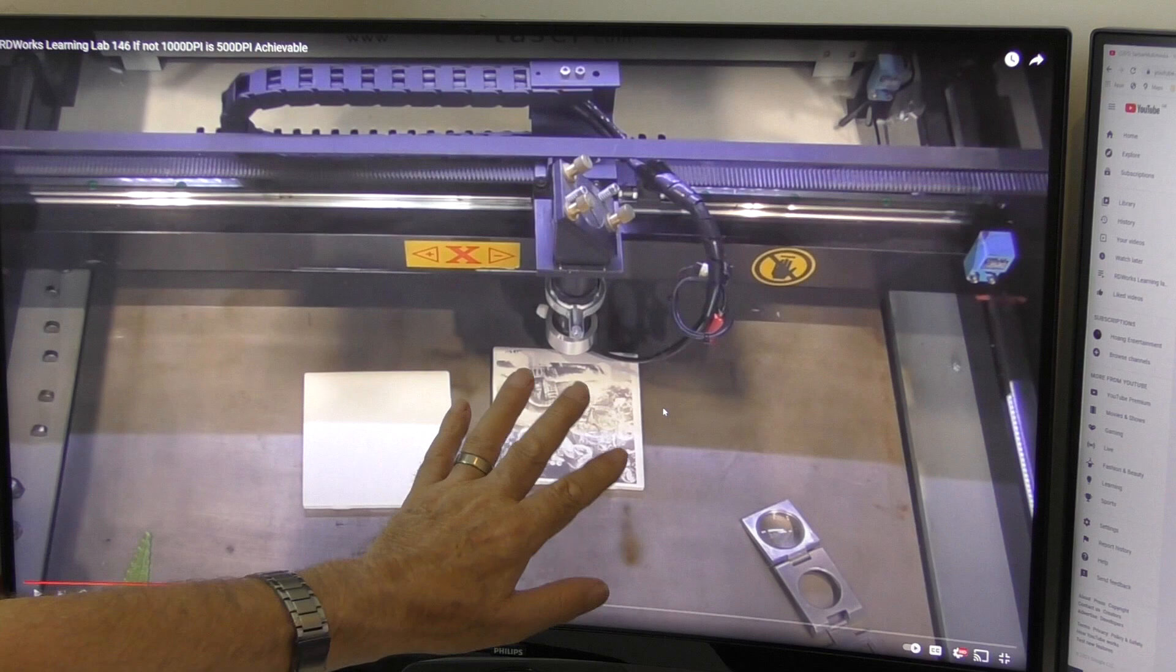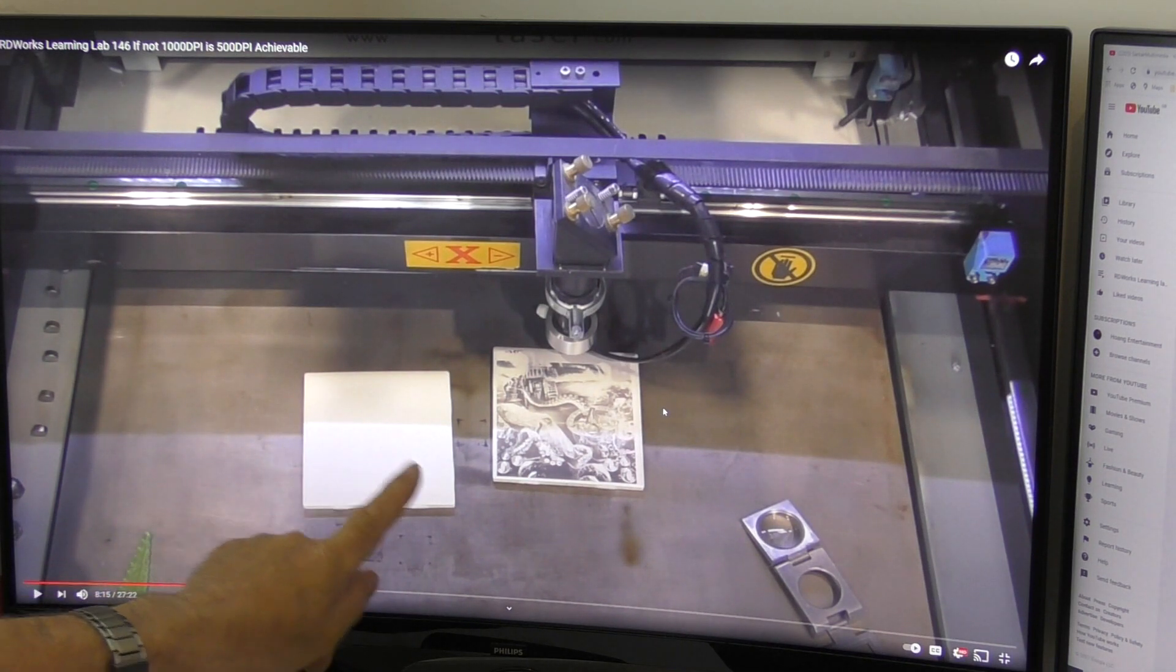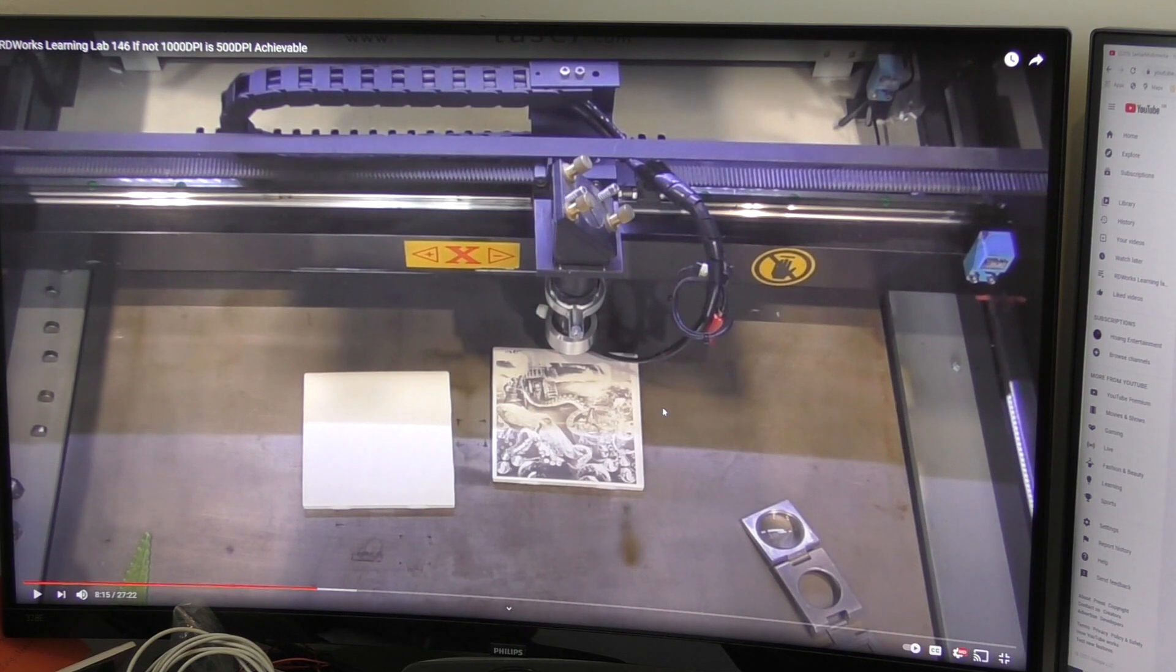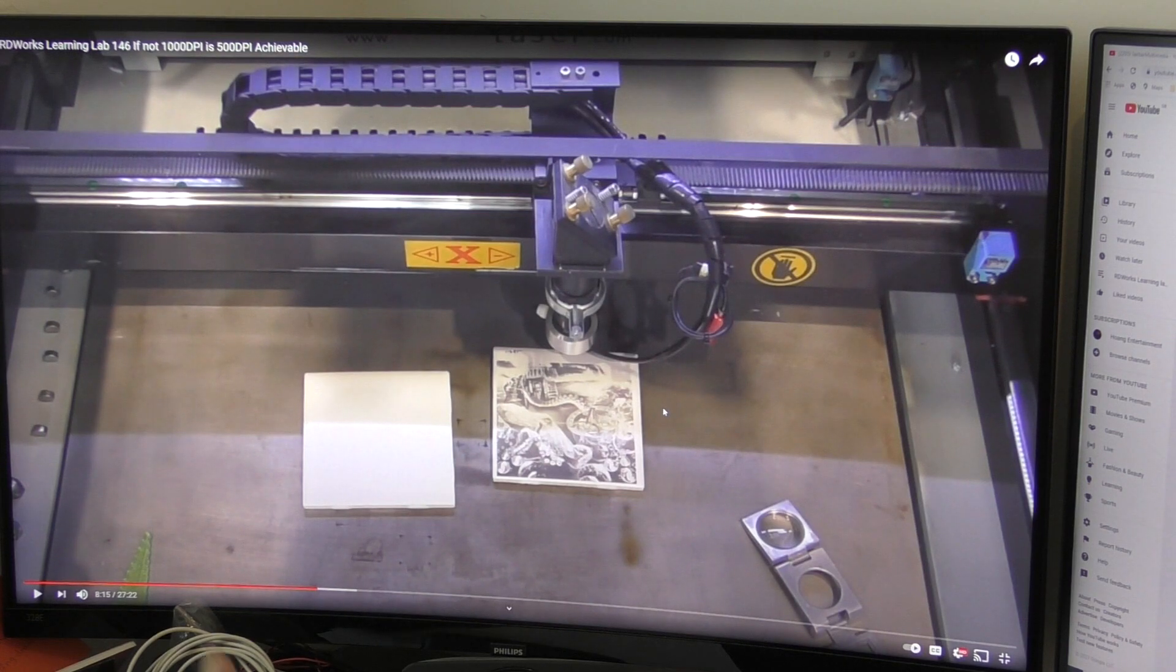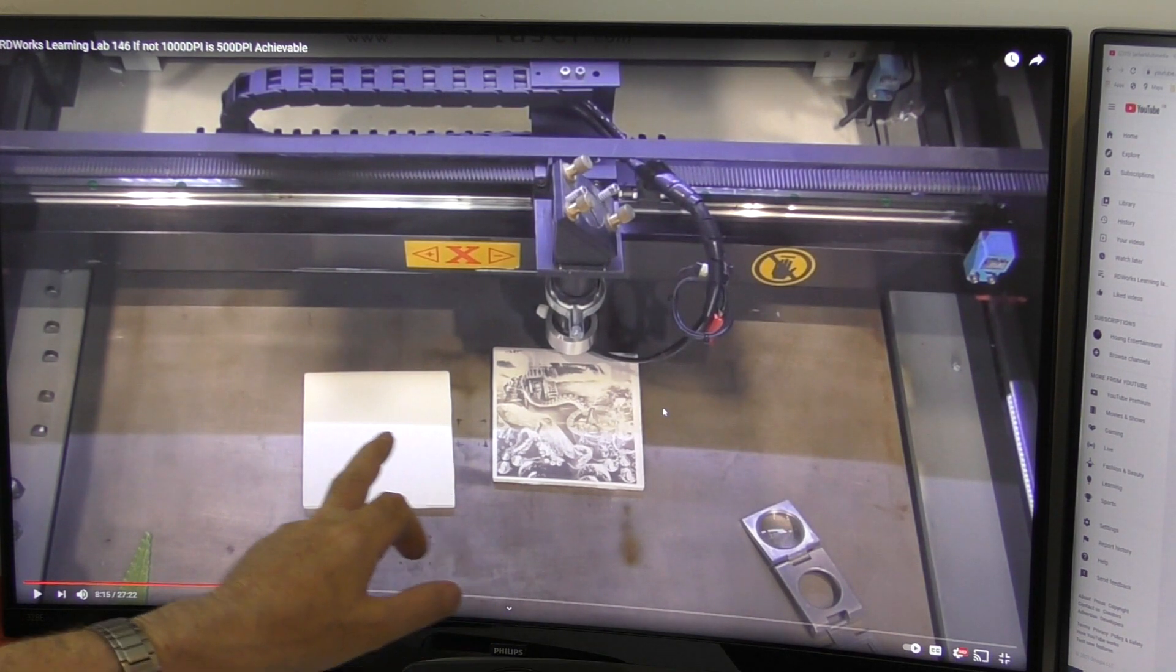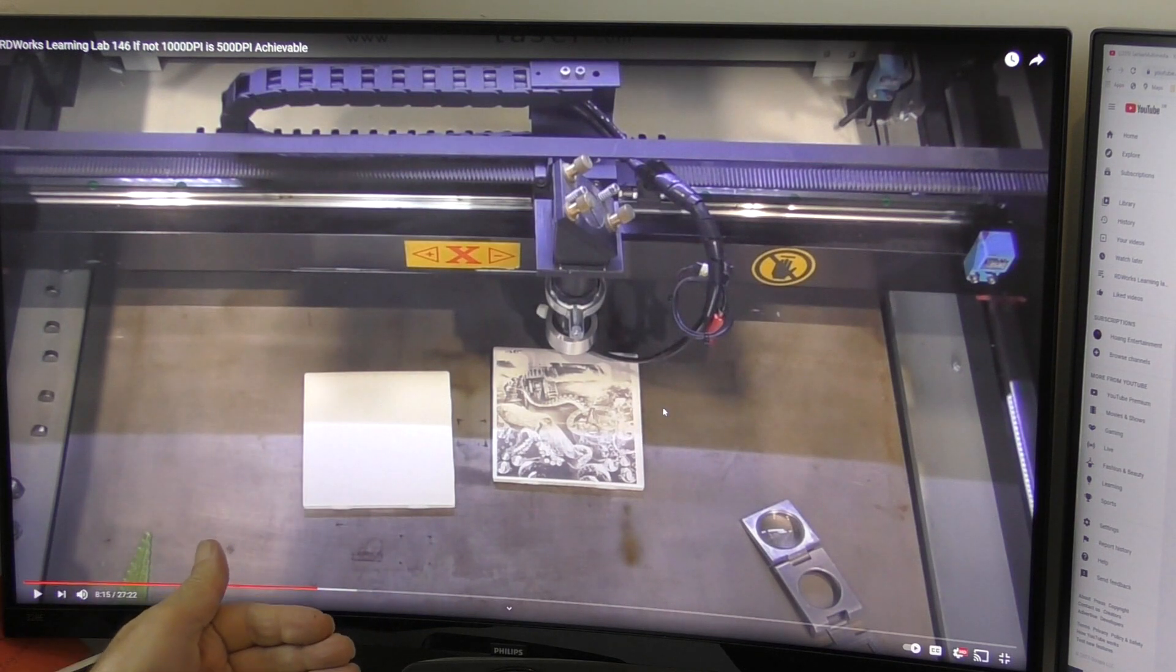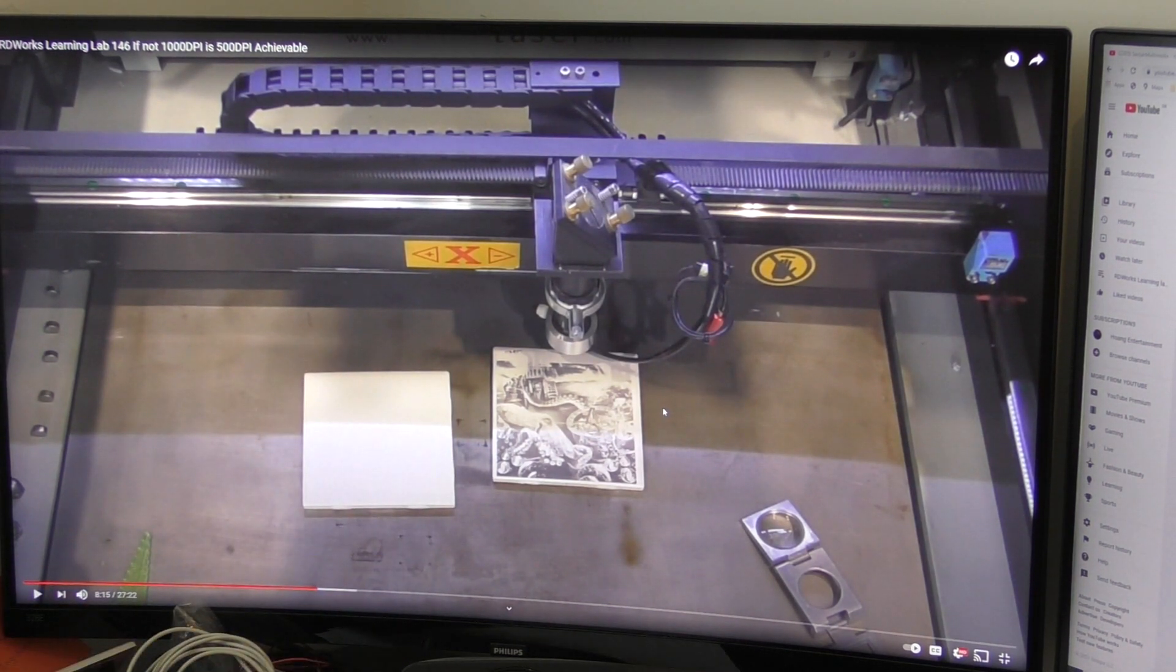I never got to the bottom of the chemistry of how these worked but in principle I fairly soon established with a little bit of research into ceramics that in essence the white background that's on the tile is something called a high temperature firing glaze which has got some sort of either mixture of or single metallic oxides in it that respond to very high temperatures. Then they cover over this special surface with a normal low temperature firing glaze so you've finished up with a white glazed tile. Now when the laser beam is very tightly focused the energy that you're firing at this surface creates a huge temperature and that temperature is enough to convert the high temperature glaze that's underneath into a black layer so we can produce black dots on a white background and leave the glaze on the surface completely untouched.